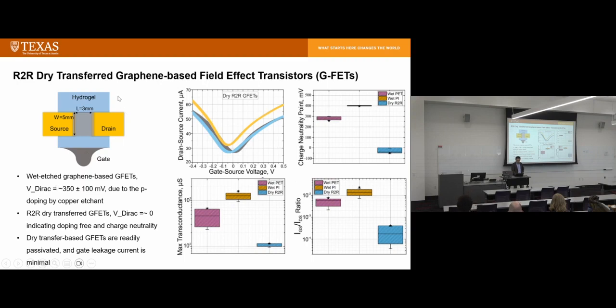So what we did is we made a simple graphene-based field effect transistor. We have a gate electrode, and on the gate electrode there is a hydrogel material. So this is a substrate, and we put our transferred graphene over here. This is a very large channel compared to what you would use working on graphene-based field effect transistors. We have a channel size 3 millimeter by 5 millimeter, and we have gold electrodes, source and drain. So we use this field effect transistor to study the properties.